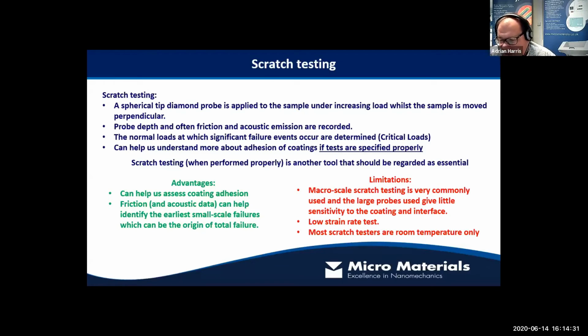commonly used size. The problem with this is that it puts a stress maximum in the sample material which is too deep. What happens is the stress maximum is in the substrate. It's not in the coating or near the interface at all, which is really what we're trying to test. So very often scratch testing is not applied in the most sensible way. So we really should be careful about how we design our tests.